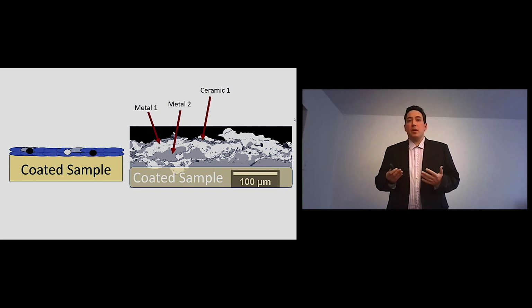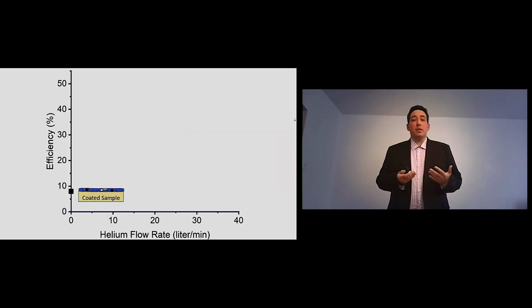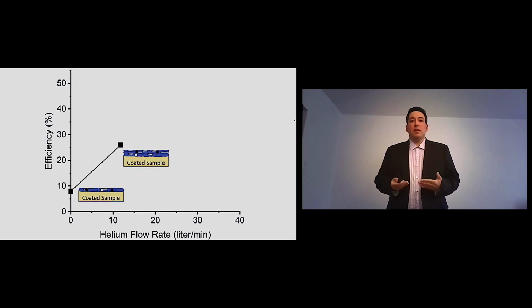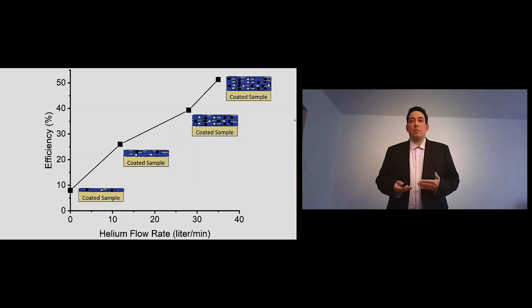In order to test that theory, we did a set of experiments, and we increased the flow rate of helium on the spray. Well, the helium has an effect of helping the heat transfer between the particle and the stream and makes the particle heat more. Furthermore, it also increases the temperature of the stream. As we start increasing the amount of helium, we start noticing more and more coating being deposited, up to the moment that we reached the limit that we had in the equipment, and we also didn't want to burn the samples anymore. So if you heat too much, the sample might be burned.